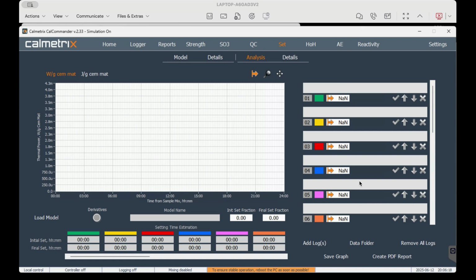So just to add to that, the 1/3, 2/3 is valid for plain Portland cement or something else that's quite reactive, or limestone calcined clay cement, but not something that's loaded with fly ash with a curve that's relatively flat. There you have to be careful with using this rule of thumb, because it's less valid when the curve is quite flat. The steeper it is, the more valid it is.